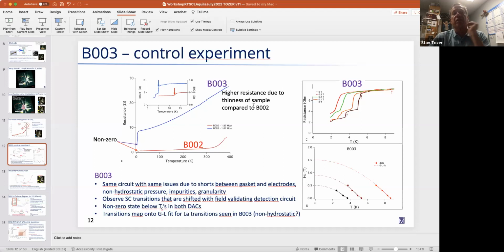And then to verify that it's superconductivity in this low temperature region, we apply a magnetic field. You can see there are several transitions here, most likely due to the fact that we have a non-hydrostatic condition in that cell, plus or minus 5 GPa. But they clearly are suppressed and they fit reasonably well to a GL fit.